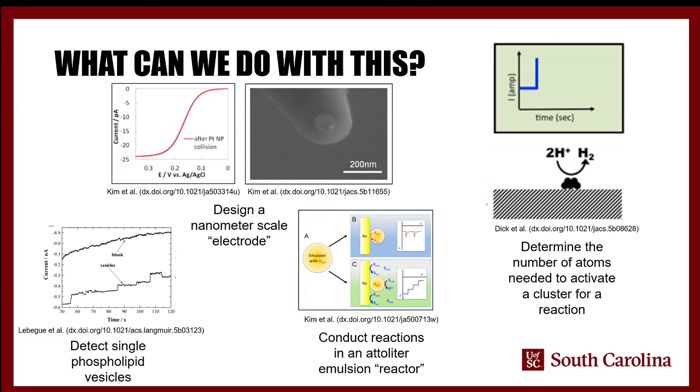And so he could find that for different metals, you had a different minimum number of atoms that were necessary. So platinum, I believe, was 5 atoms. I think nickel was like 7, copper maybe was 7 or 9. But it's not the exact same number of atoms to achieve this catalytic reaction.